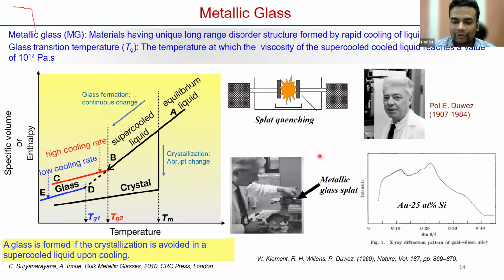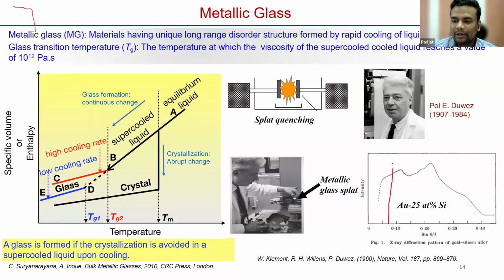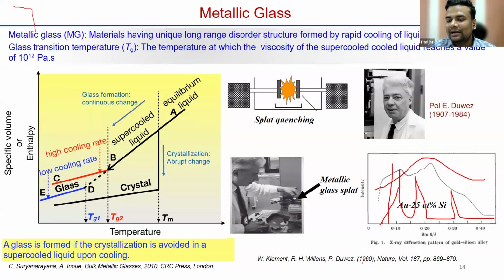And when he examined that material in X-ray diffraction, a polycrystalline metal will show peaks like that. But after doing this experiment, he didn't find any peak. Rather, he found a broad diffraction maximum. So with this single XRD plot, he published one paper in Nature in 1960. That was the discovery of a metallic glass.